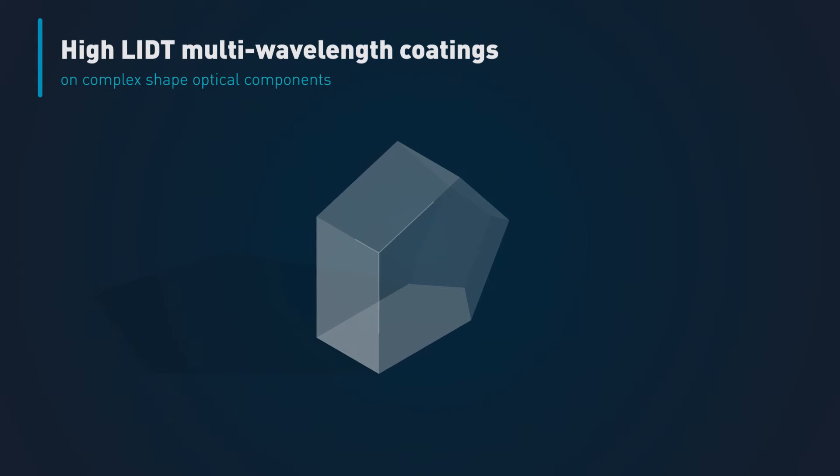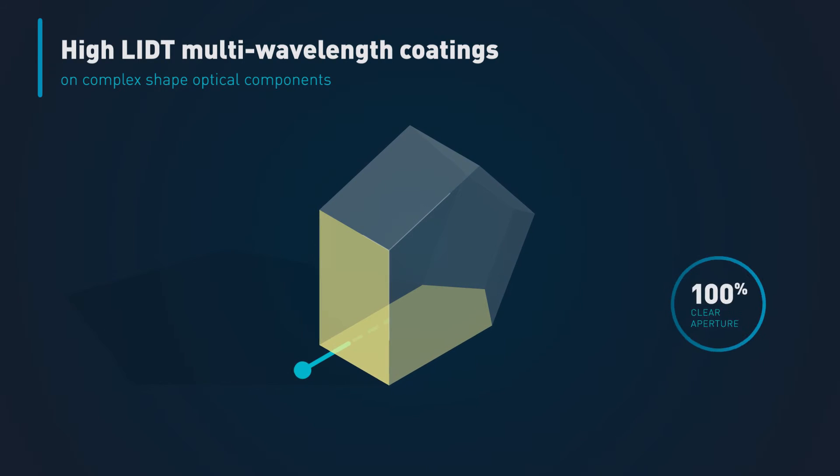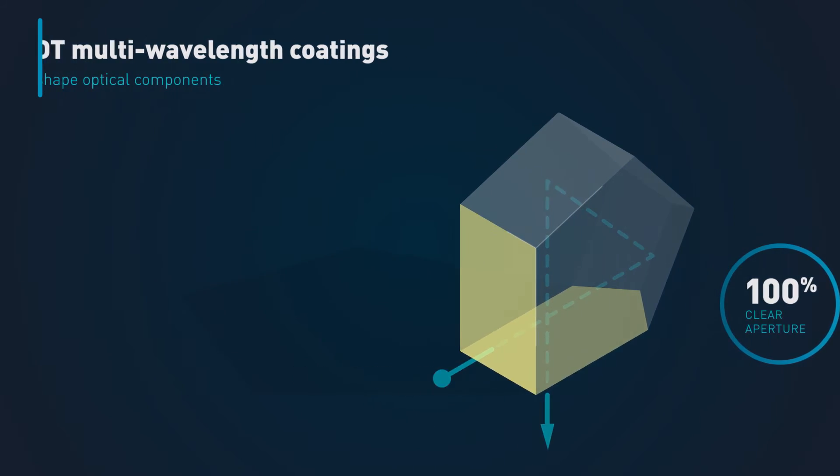For a client from the defense aerospace industry, we came up with a solution for applying high-LIDT multi-wavelength coatings to complexly shaped optical components. In order to meet requirements for a strict clear aperture and high laser-induced damage threshold, we designed special substrate holders to ensure 100% clear aperture for all facets.